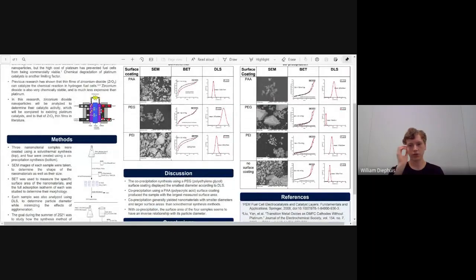2 important discussion points about these results are, first of all, that the coprecipitation results on the right are generally more desirable than the solvothermal results. All 4 of the coprecipitation samples have higher surface areas than those of the solvothermal samples, and they generally have smaller diameters as measured by DLS.